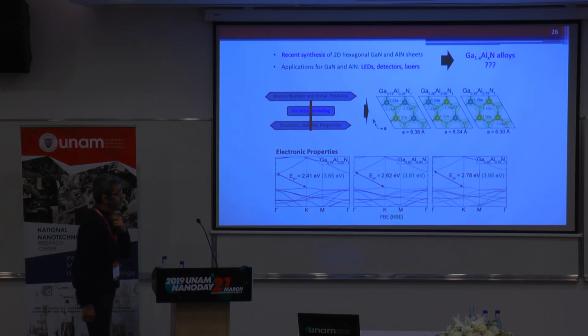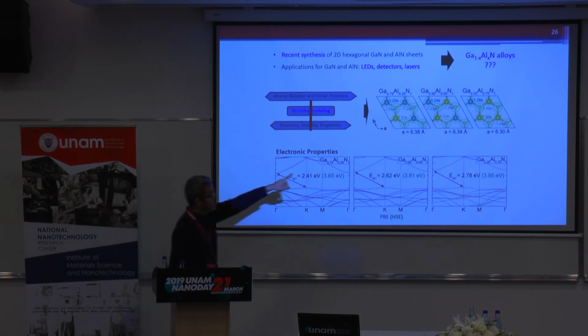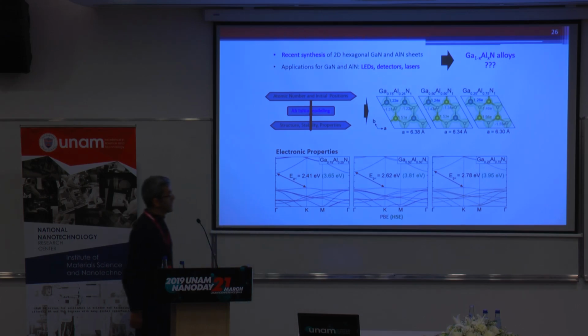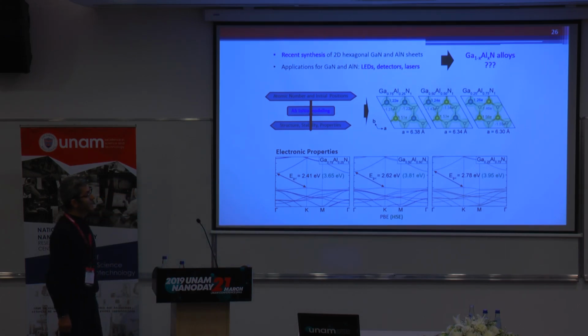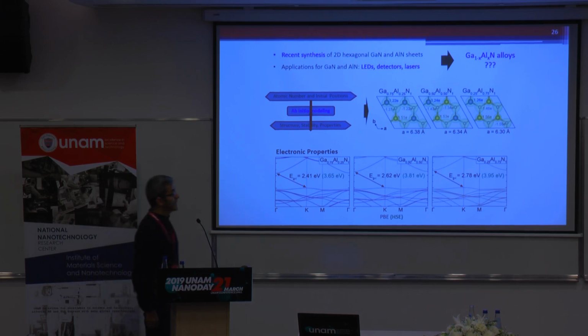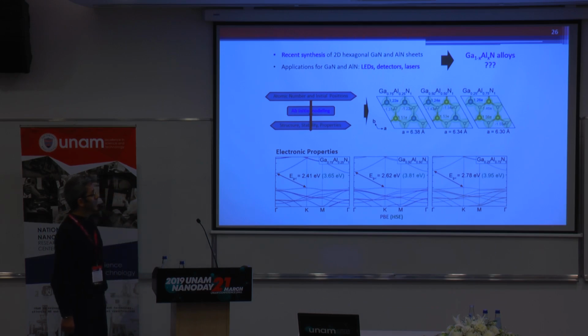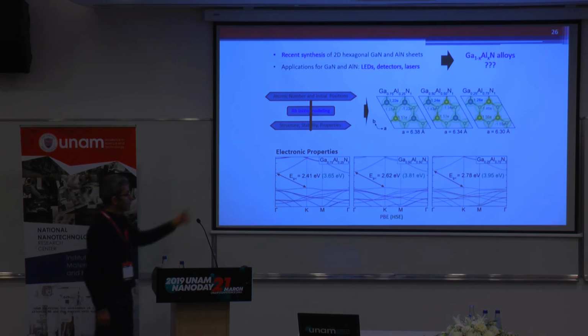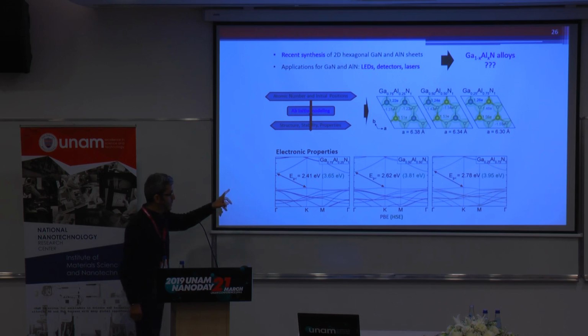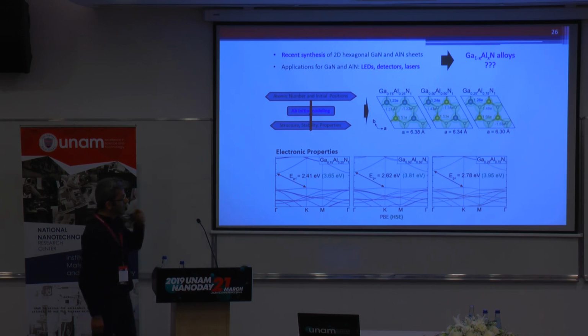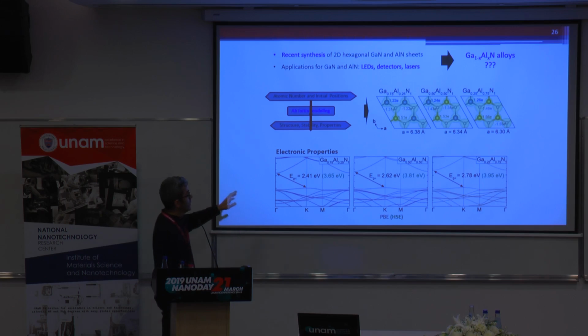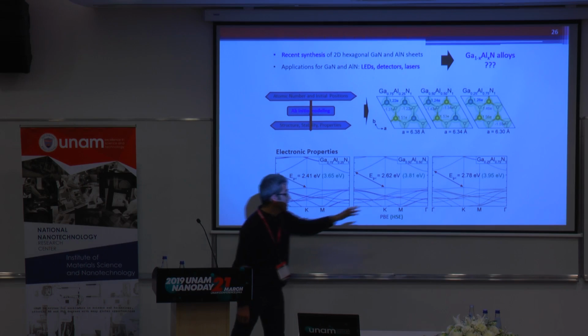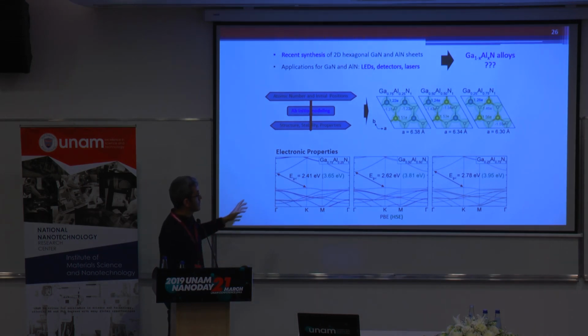According to our calculations, these ternary alloys are stable at 0 Kelvin and preserve their stability at 300, 600, and 900 Kelvin, according to our phonon distribution and MD calculations. From now on, I will show electronic properties, thermal properties, and optical properties, and conclude. For electronic properties, I didn't put the gallium nitride and aluminum nitride versions for crystal structure and electronic properties because they have been studied already.